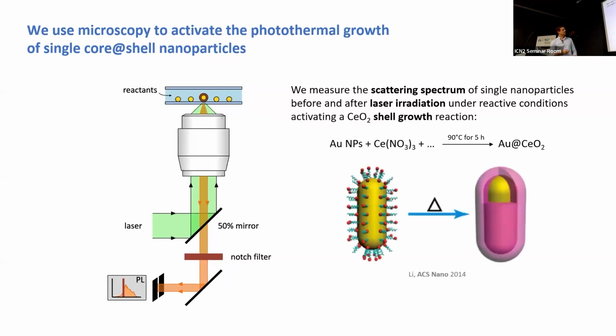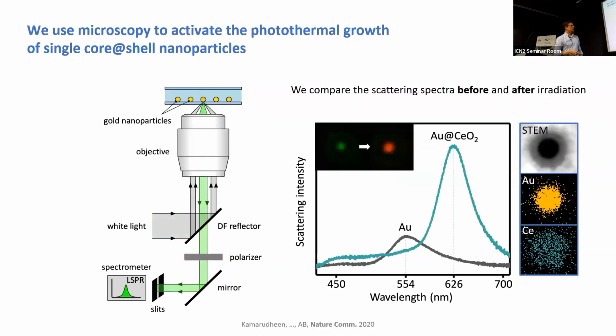The kind of reaction that we wanted to activate is a ceria growth reaction. So it's cerium nitrate, and if you heat it up at 90 degrees C for 5 hours, you can generate a shell. So we know that this reaction is temperature activated. So we did it on many single nanoparticles, and a typical experiment looks like this.